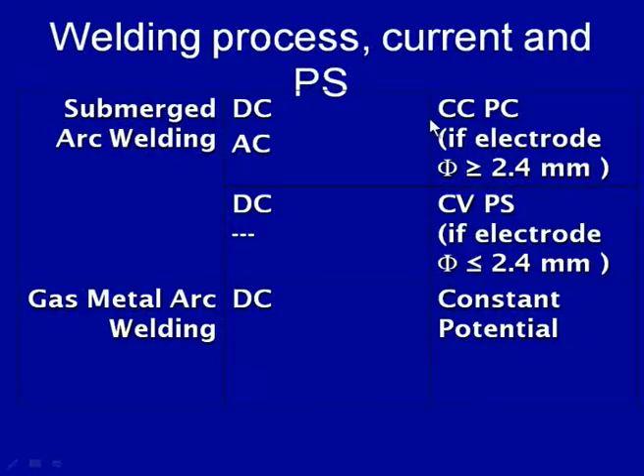Therefore, the constant current type of power source is used, so that the heat remains largely constant due to the constancy in current when a large diameter electrode is used. To take advantage of the self-regulating arc to maintain the arc length in submerged arc welding processes, DC is used, especially when the diameter of the electrode is less than 2.4 mm.